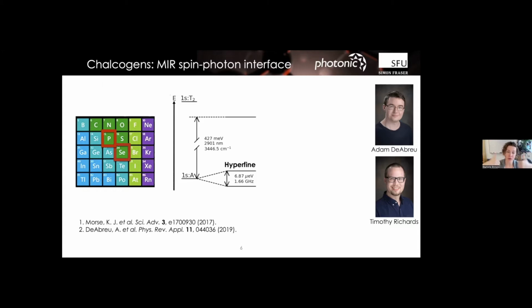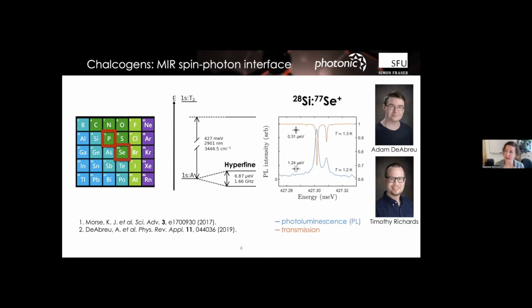So these are orbital transitions, and with orbital transitions you would expect a higher quantum efficiency, and they did. This one was in the couple percent. So again, a couple orders of magnitude short, but not really what we wanted. But it did give us the kind of luminescence properties. It started to seem right. Like you could see that it was emitting spin entangled photons. You could have absorption, that kind of thing. It was encouraging.